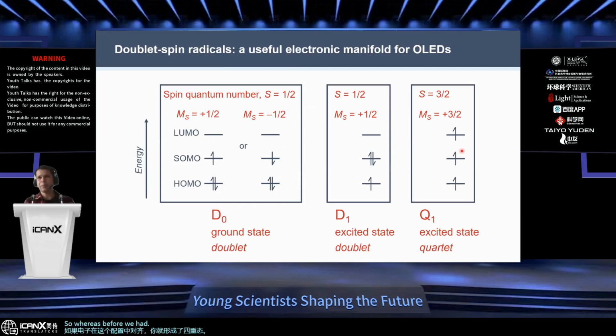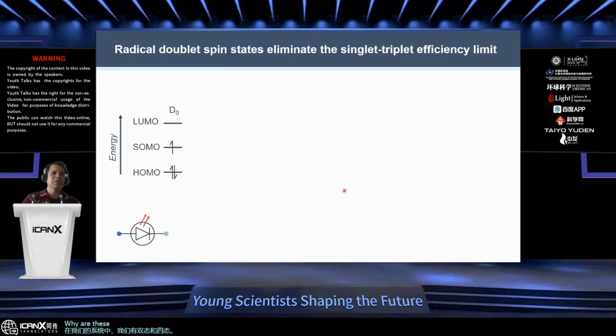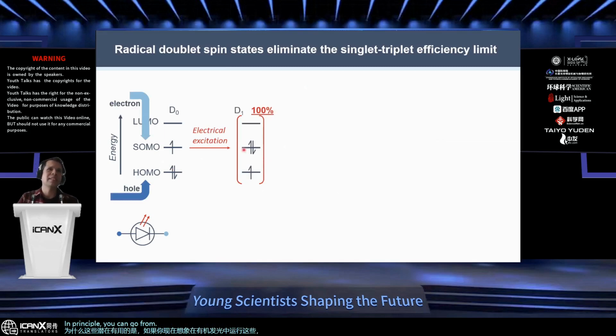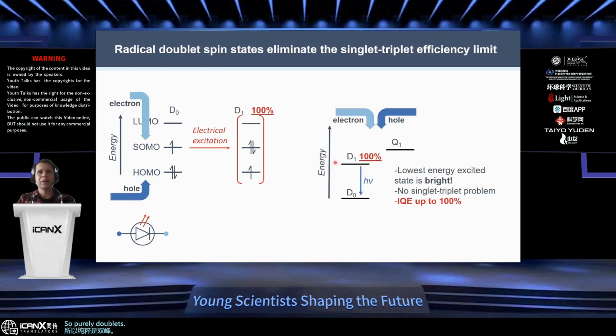So whereas before we had singlet and triplet states formed in non-radical, more conventional materials, in our systems, we have doublet and quartet states. Why these are potentially useful is that if you imagine running these in an organic light emitting diode, in principle, you can go from a doublet ground state to purely doublet electronic excitations. And now in these materials, your lowest energy excited state is bright and luminescent. You can get fluorescent transitions from these systems. And in principle, you totally avoid this singlet triplet spin statistics problem.